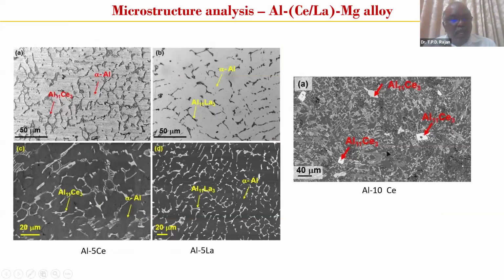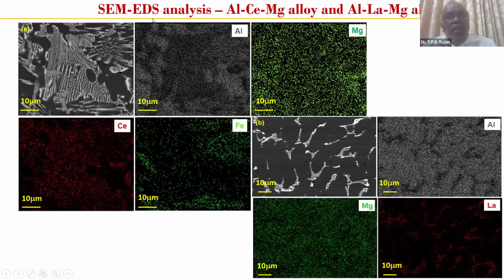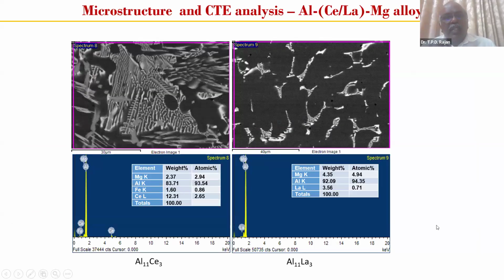So this again shows the formation of the aluminum-cerium precipitates. These are the precipitates which the optical microstructural evaluation shows, and the SEM micrographs also show very fine precipitates of aluminum-cerium in the alloy. This shows scanning electron microscopy with the dot mapping of EDX, which shows a very fine percentage of cerium. Again, in the case of lanthanum also, the final precipitates are dispersed along with this. You can see these are all present in the grain boundaries. These are the precipitates of lanthanum, and we can clearly see them in the microstructures. Again, a similar structure with EDX mapping.